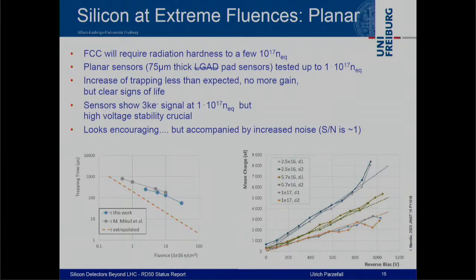There are two plots at the bottom showing what they do. Looking at this plot of trapping as a function of fluence, trapping of course increases as you keep irradiating, but not as badly as you would expect if you extrapolate from lower radiation doses.